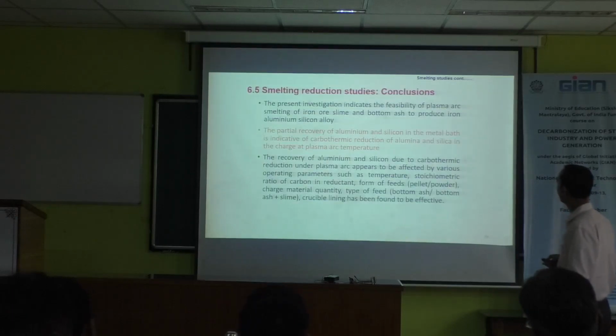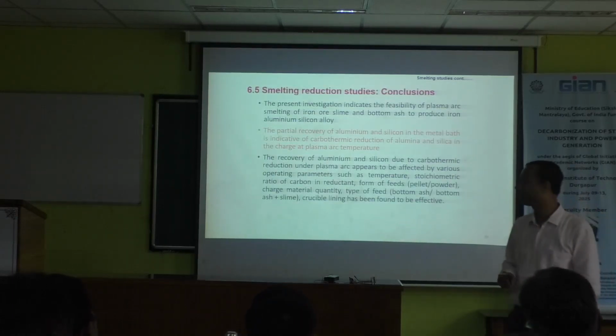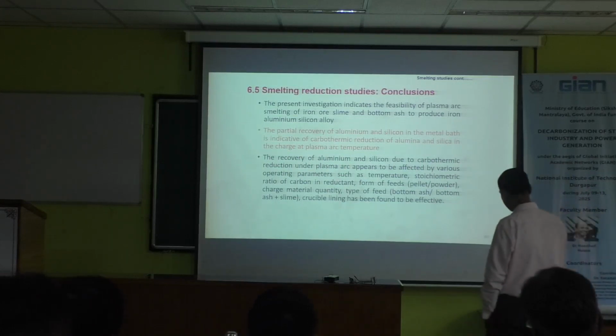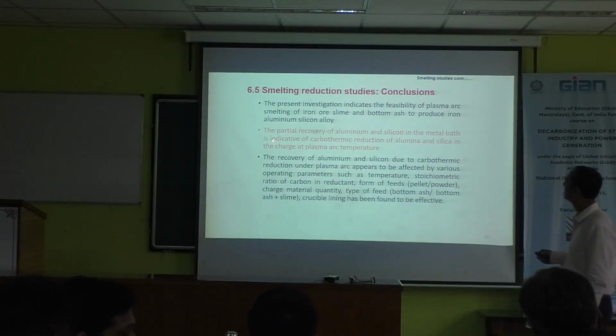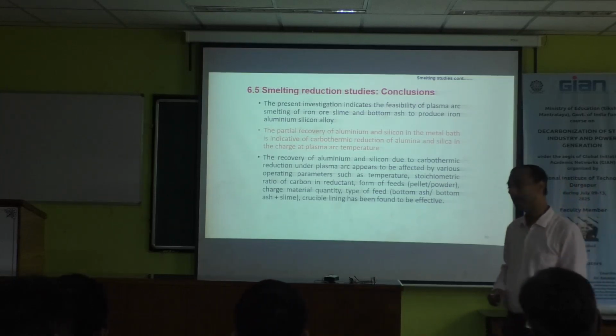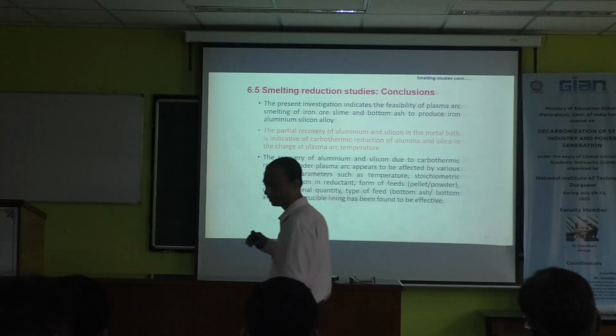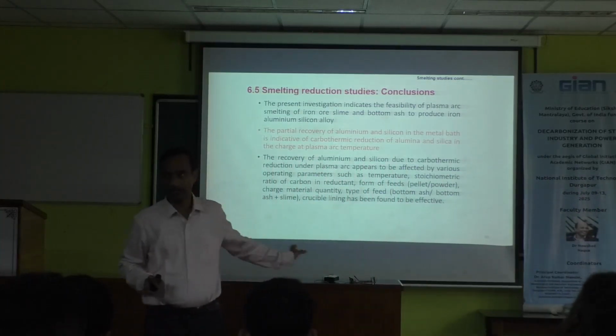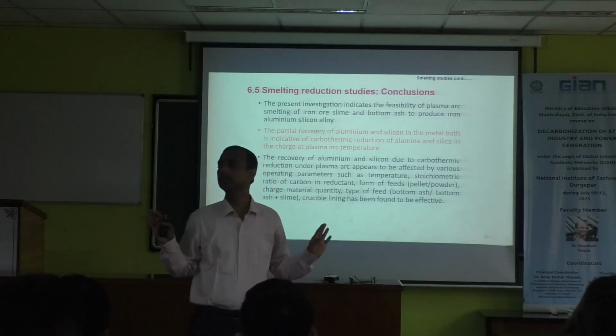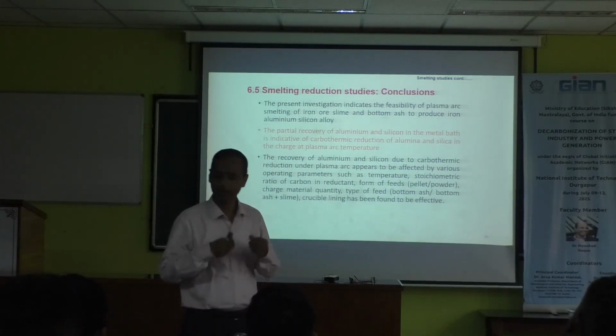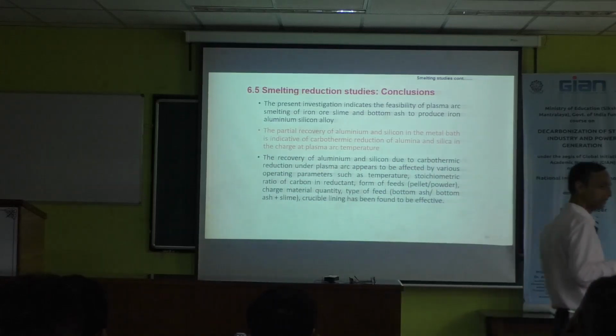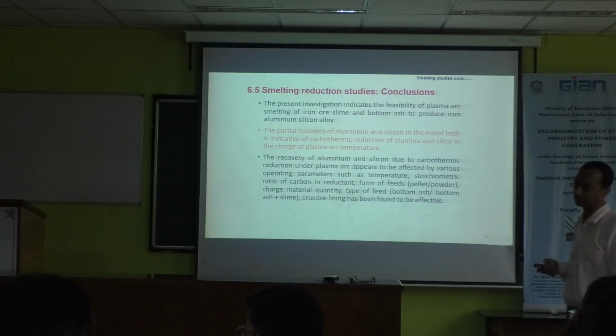Ultimately, what we concluded from this study: the partial recovery of aluminum and silicon in the metal bath indicates the carbothermic reduction of aluminum and silicon in the charge. It means as we use carbon content, in nitrogen plasma also you can get the metal, meaning you can recover the metal, but it can be enhanced by using the hydrogen plasma. Then the carbon percentage in the charge mix or the pellets can be decreased.